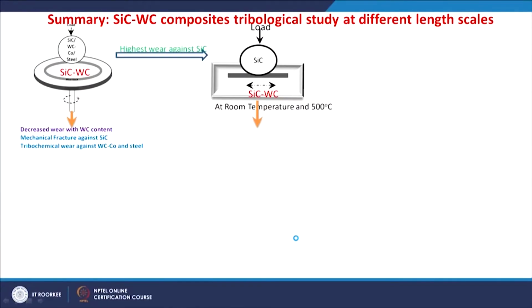So, finally summarizing, we have gone through the salient results obtained in the tribological study at different length scales for the silicon carbide tungsten carbide composites. So, we found wear was decreased when tungsten carbide content is increased in unidirectional sliding conditions as well as the reciprocatory sliding conditions, whereas mechanical fracture is found against silicon carbide ceramic ball in unidirectional sliding conditions. Tribochemical wear dominates against tungsten carbide, cobalt or the steel ball.